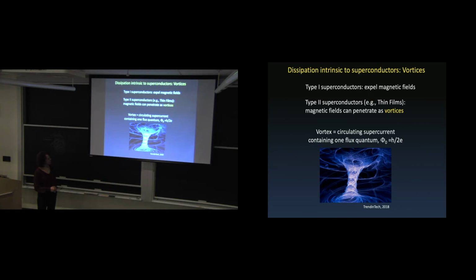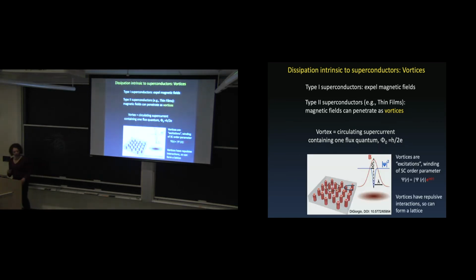Okay, so what is this? I don't know what this is, but we're talking about something that has an analog to this, which is basically an excitation of a superconductor. An excitation of a superconductor is dissipative, so that's relevant, right? And the excitation is a magnetic field penetrating, with a flux quantum through a superconductor, and to shield it from the rest of the superconductor, there's a circulating current, supercurrent going around it. Okay, so in thin film superconductors, magnetic field penetrates as vortices. One vortex has a circulating supercurrent that contains one flux quantum. Okay, and that's a vortex in a superconductor. And most of the time it's shown with more boring pictures like this.